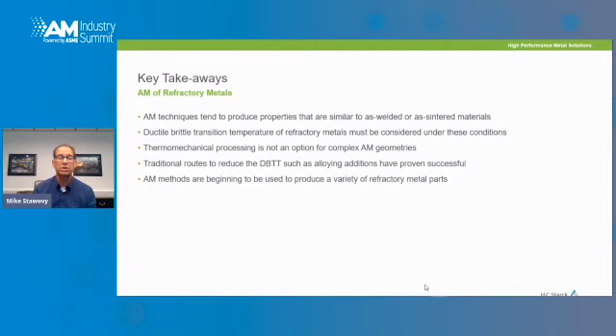And so what you need to be conscious of is the ductile-to-brittle transition temperature of refractory metals, and those must be considered under those kinds of conditions. You've got to remember that thermomechanical processing is not really an option for the complex AM geometries, and so traditional routes to reduce ductile-brittle transition temperatures, such as alloying additions, we've proven to be a successful alternate path as opposed to thermomechanical processing. And so we see that these AM methods are beginning to be used to produce a variety of refractory metal parts.